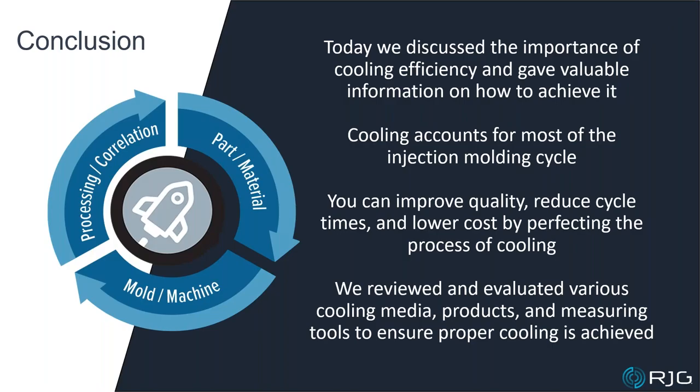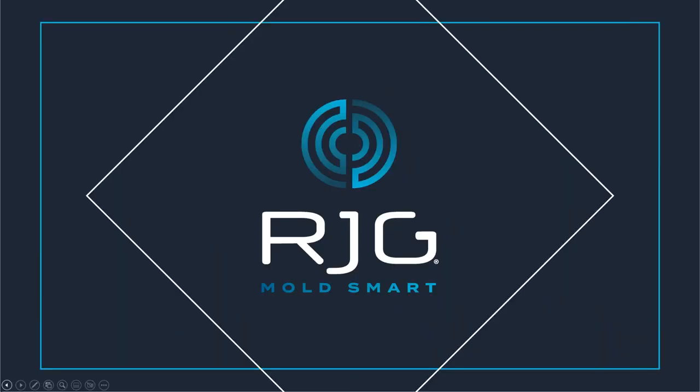So to conclude, today we discussed the importance of cooling efficiency and gave valuable information on how to achieve it. Cooling accounts for most of the injection molding cycle time, 80% to be exact, from a plastics point of view, and you can improve quality, reduce cycle times, as well as lower costs by perfecting the process of cooling. We also reviewed and evaluated various cooling media, products, and measuring tools to ensure proper cooling is achieved. That's all I have for today.